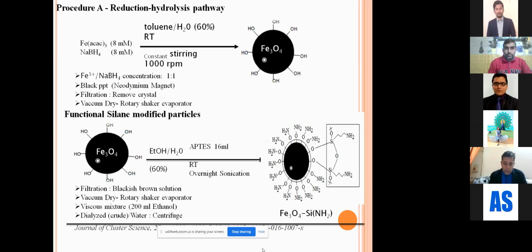So this we have already published in the Journal of Cluster Science, and we have also published this entire mechanism in Materials Today Proceedings. This is the method actually being utilized for the chemical synthesis of SPIONs, where the reduction hydrolysis pathway is followed, where you are using ferric acetylacetonate along with sodium borohydride, in the presence of either an organic solvent or water as a solvent. So this is where we have conducted the experiment.